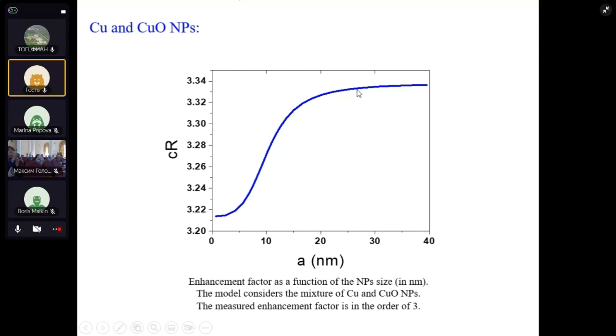And we see that for the particle size described by the group of Professor Renata Reisfeld in the case of copper, we see a very satisfactory agreement between theory and experiment. And this was published recently in the Journal of Luminescence. I forgot to put the reference here, but it just appeared, and I can send the reference to you if you are interested.